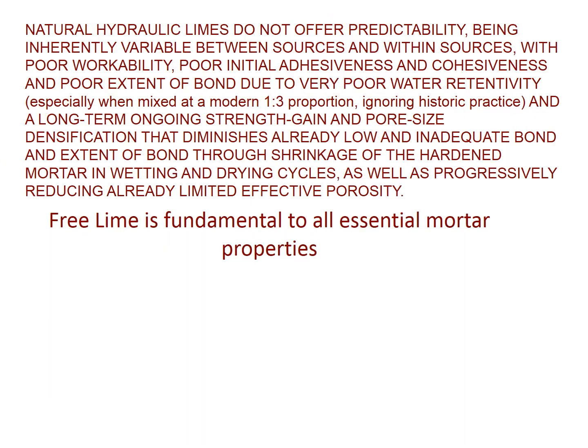Natural hydraulic limes do not tend to offer predictability, being inherently variable between sources and within sources, with poor workability, poor initial adhesiveness and cohesiveness, and poor extent of bond due to very poor water retentivity, especially when mixed at a modern 1:3 proportion, ignoring historic practice. NHLs were mixed at 1:1 or 1:2 historically, and a long-term ongoing strength gain and pore size densification diminishes already low and inadequate bond and extent of bond through shrinkage of the hardened mortar in wetting and drying cycles, as well as progressively reducing already limited effective porosity. Free lime is fundamental to all essential mortar properties.